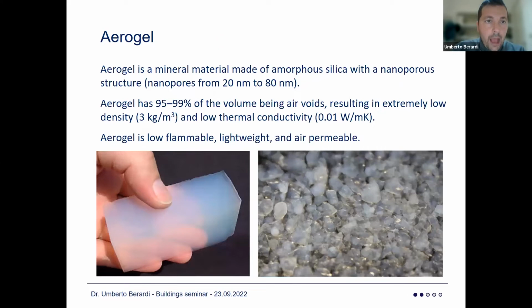So I've been working on aerogel, at this point a very old material, because it was discovered 90 years ago. So it's not really a new material at all. It's basically made of air at the end of the day. It's full of void. There's not that much material. It's 98% void at the end of the day. But thanks to the extremely low density, typically in the range of a few kilos per cubic meter, it is capable of achieving an extremely low thermal conductivity.